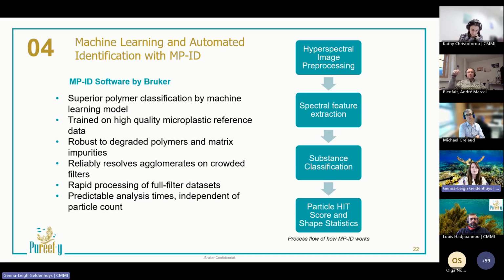It starts by dividing hyperspectral images into overlapping tiles. Pixel spectra are standardized, and then a neural network extracts relevant spectral features, resulting in a feature vector per pixel. All effects originating from noise and baseline variations are also filtered out at this step. Next, each pixel is classified into materials, like the various polymers, cellulose, calcium carbonate, and it also considers spatial context for smooth mapping. Lastly, connected pixels form particles, which are then scored against a reference library using a hit score, which users can tune themselves. A higher threshold for confident matches and a lower threshold for more inclusive identification. But rule of thumb is that a default value of 800 is a good start. So from pre-processing to particle scoring, MPID turns raw hyperspectral data into reliable, regulatory-ready results.